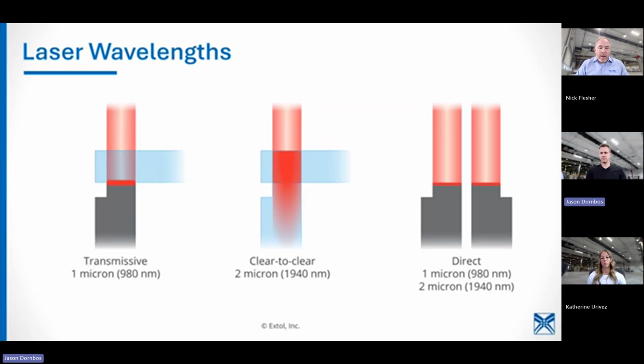Max, in your question, if there's an air gap, if that plastic's allowed to absorb that IR energy, it usually will oxidate. Whereas if you have good intimate contact, there's no oxygen getting to the surface. And so that energy that's getting poured into that surface is actually conducting up into the part. In rare cases, if the laser's on for 20, 30 seconds, we have seen blistering. But that's rare, and we can typically process that out if you have proper transmissive properties.